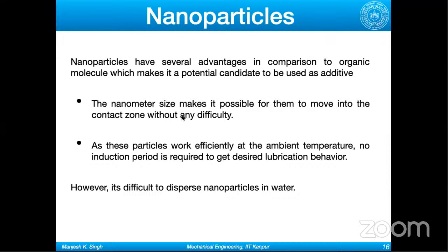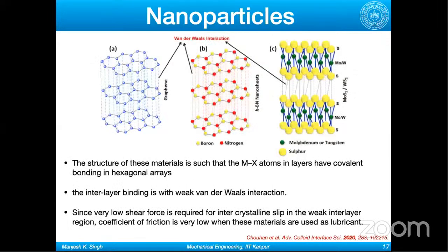The nanometer size makes it possible for them to move into the contact zone without any difficulty. Just like oil moves into the contact zone easily, these nanoparticles, because of their small size, will move into the contact zone easily, and the water will do the same thing as it was doing in oil in water emulsion. It will simply transport these nanoparticles into the contact zone, as it was doing before with the oil. And these nanoparticles, because of their layered structure, can shear easily, and that's why they will give lower friction.